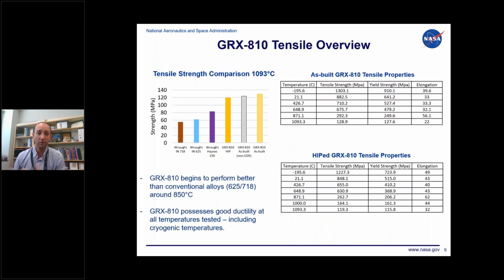So we started to do tensile testing through a wide range of temperatures. Notably, it does have decent cryogenic temperature performance, high strength, and high ductility, even with those nanoscale oxides incorporated into the part.